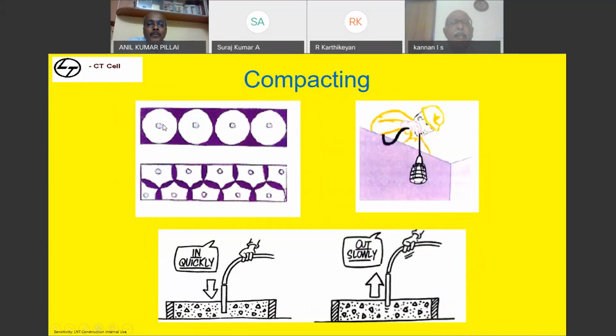Generally we use a 40 mm needle or 60 mm needle for compaction. Nowadays, most of the concrete we are making is more than 75 mm slump. If it is a 40 mm needle and the slump is more than 75, it can compact 250 to 350 millimeter area only. If this is a 60 mm needle, it can compact 400 to 500 millimeter. That's all, 400 to 500 millimeter area only. That means beyond 500, even though I am able to stand here and feel the vibration, the concrete is not getting compacted. Let us be very clear about the process. If you are using a 60 mm needle, every 1 feet you have to insert a needle so that you are overlapping and compacting.